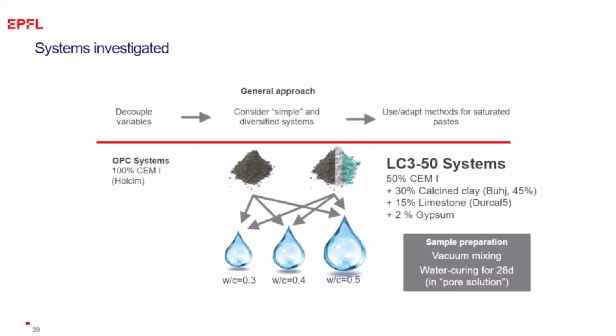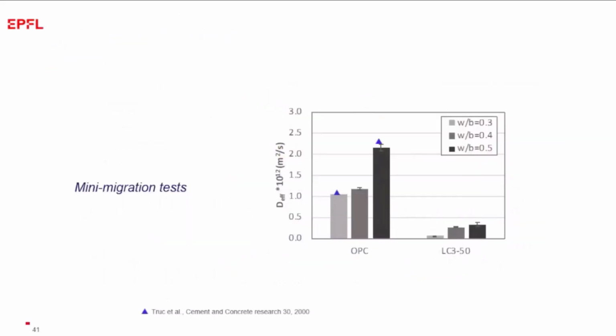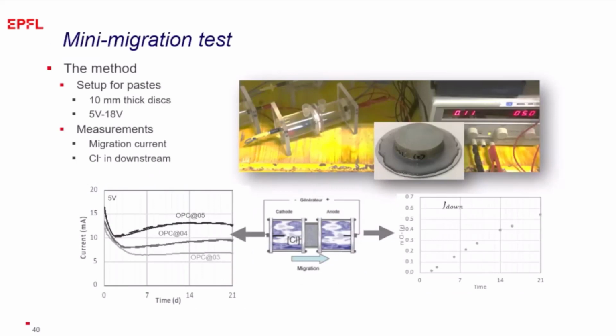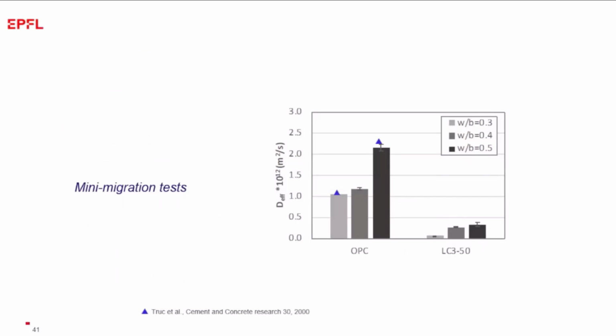And then when we studied a wider range where we looked at the impact of water-cement ratio, and we studied it in this new mini migration test, looking at the flow of chloride through these paste samples, what's really interesting is we see that all the calcined clay blends, so even the calcined clay at a water-cement ratio of 0.5, is better than the Portland cement even at a water-cement ratio of 0.3. So of course we know water-cement ratio is important, but we've got impact in the calcined clay way beyond that.